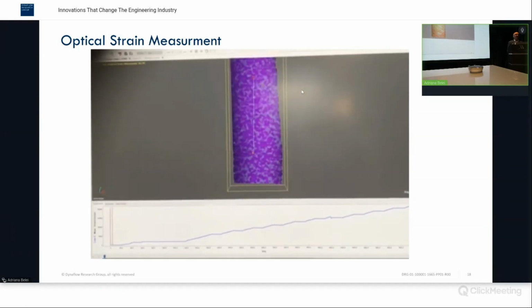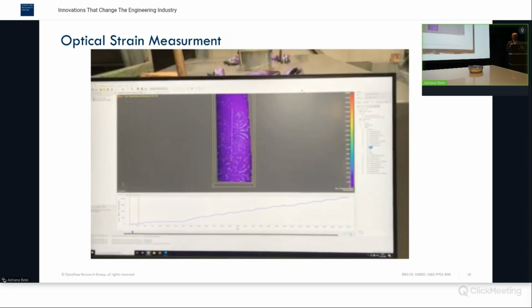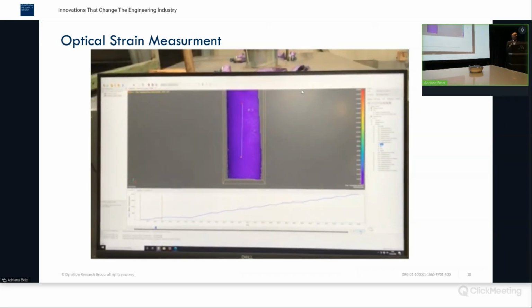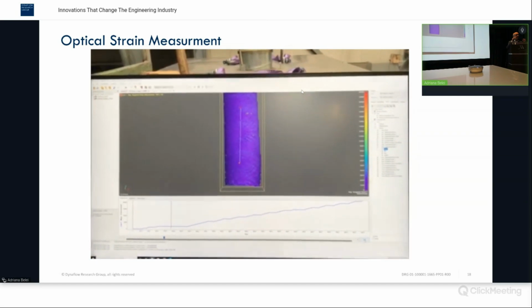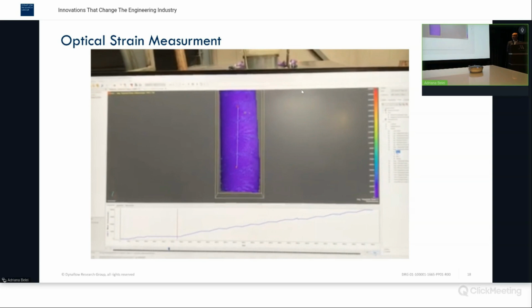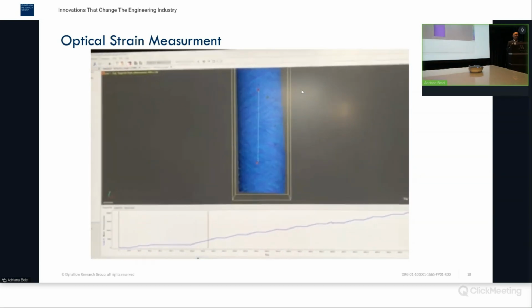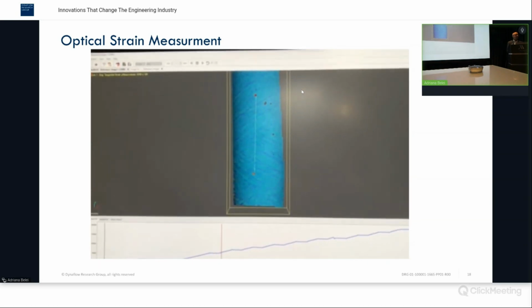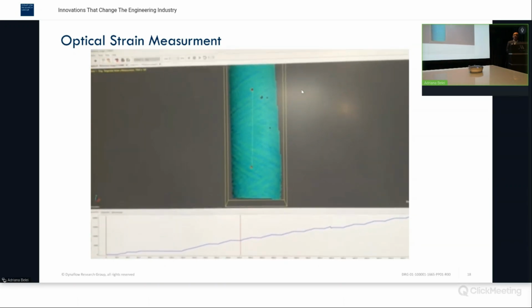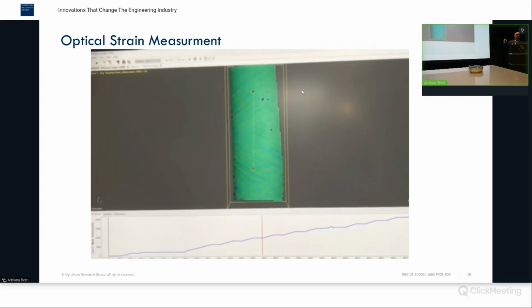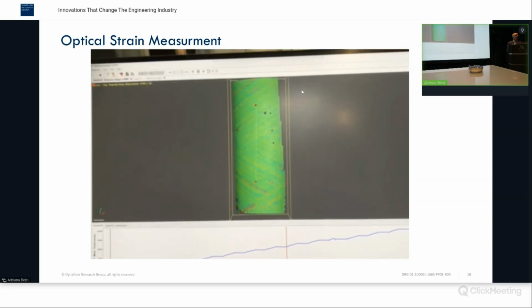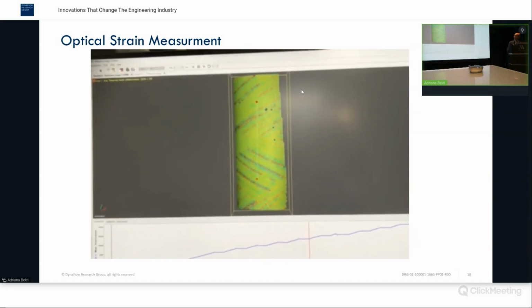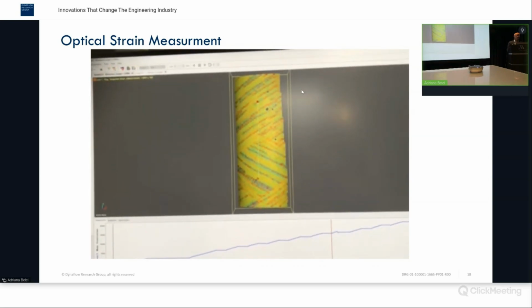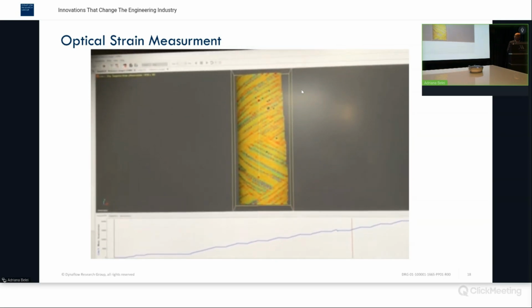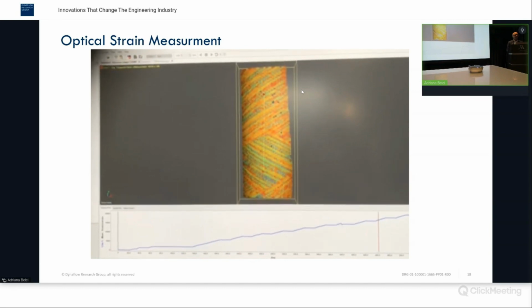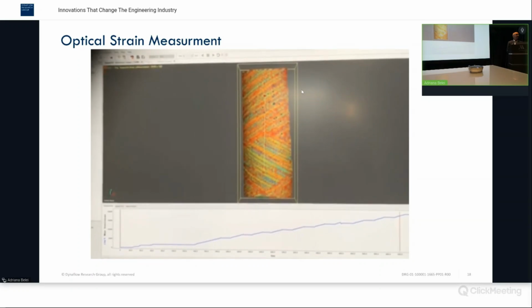So the way it works is you apply a coating on the pipe material, and you measure strains over the whole area between specks in the paint itself. So you can do a lot of statistics: average measurements, means, standard deviations. It appears that a deviation from linearity of the standard deviation of the whole strain map seems to coincide with the onset of crack development. Unfortunately for the 2560 that didn't work, so this is a start and a recommendation to look at whether we can use this methodology in the future.